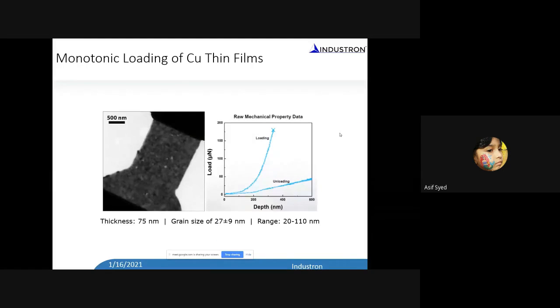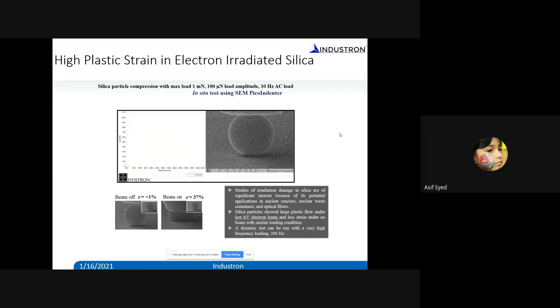Now, same thing, we can do tensile test experiments. This is a copper film, also done inside a transmission electron microscope, and you can record that. And this is an experiment done inside a scanning electron microscope. This is a silica particle being compressed. I'm going to show the video. It's a compression of that, and then you can do a fatigue test on this silica particle. This particle is about 1 micron in size, and you can see how much plasticity it goes through. We found that with the electron beam, we can deform this material to very high strain, and you can do fatigue tests.